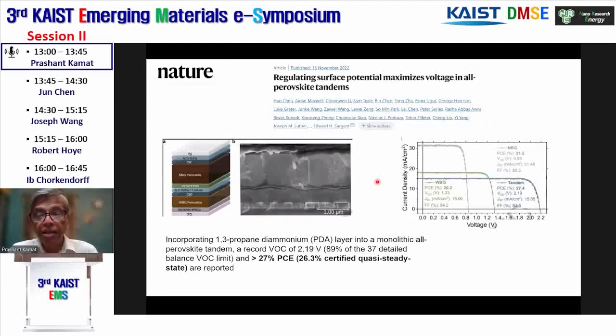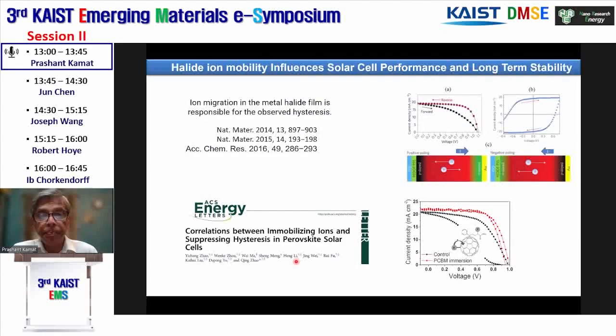Here is the latest on all-perovskite tandem cells, in which they created a wide band gap perovskite and a narrow band gap perovskite, and then combined the two, along with ALD-deposited tin oxide and a hole transport layer. With that, they were able to reach up to 27% PCE. So this is just out in Nature. Okay, so that is great. We are getting very high efficiencies. But when it comes to long-term stability, this still seems to be a major hurdle that we need to overcome.